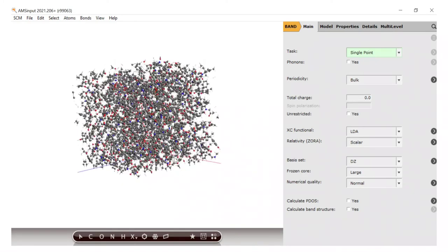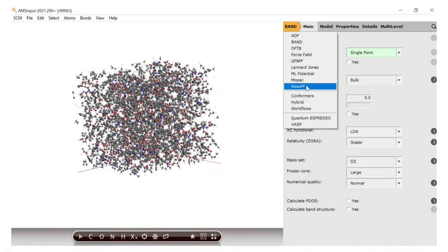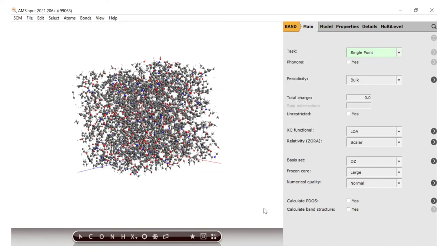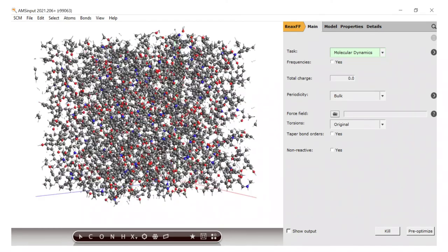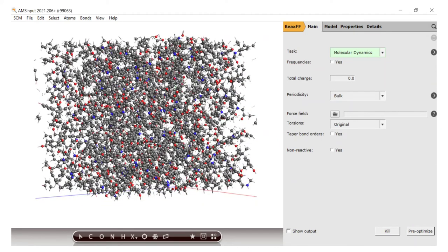Then we switch to the ReaxFF engine. There you go. And set up an annealing program. The data points will be sampled within the temperature range of 300 to 340 K. However, before the actual sampling, I will carry out a short simulated annealing sequence. I find this step produces less noisy results in the end. I guess if the sampling intervals are chosen long enough, the simulated annealing can also be left out.